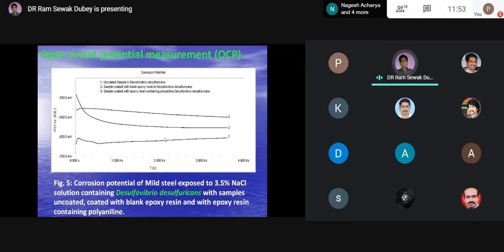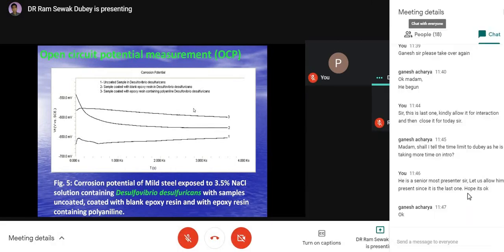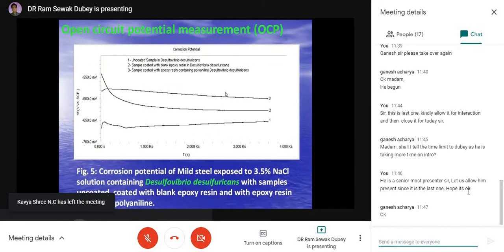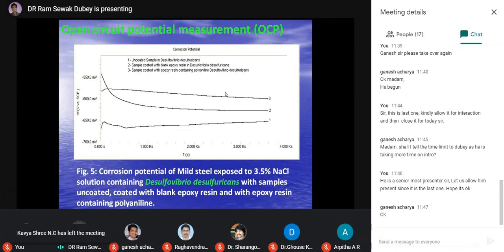Corrosion potential with respect to time is shown here. As is clear, number 1 is for the uncoated sample in Desulfovibrio desulfuricans, and the last, number 3, is the variation of open circuit potential for the epoxy resin containing polyaniline exposed to Desulfovibrio desulfuricans. It is observed that the open circuit potential shifted considerably towards the positive direction, which indicates that polyaniline is acting as a good inhibitor, a good controller of corrosion in 3.5% NaCl, that is seawater, containing the microorganism Desulfovibrio desulfuricans.